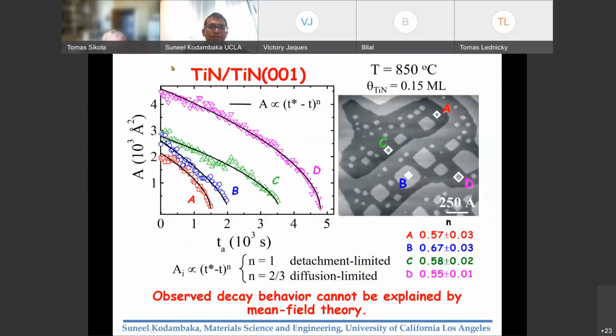But experimentally, typically, when you do these experiments with small size clusters, the mean field theory model fails to explain the observed behavior. And let me tell you why. So this is another experiment. Again, these are islands. And from the time-lapsed images, we can measure the areas of these islands. And I've only highlighted 4 of them here.